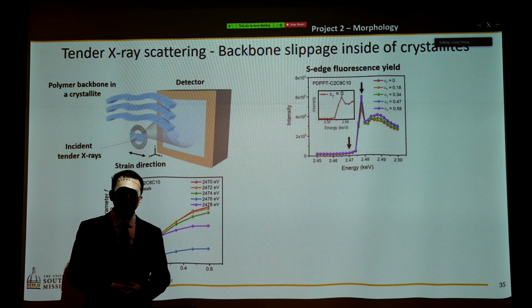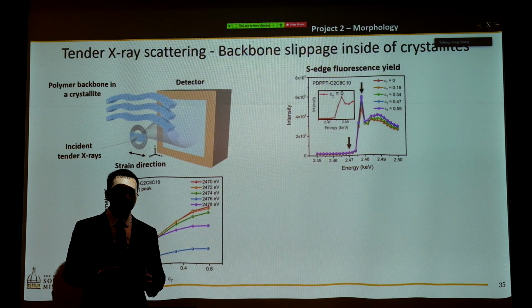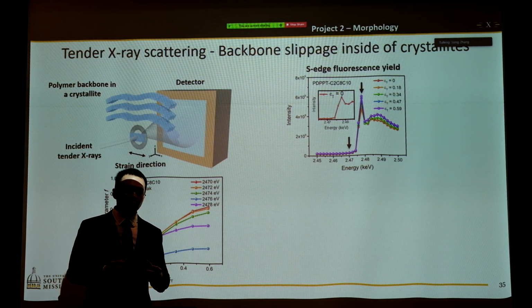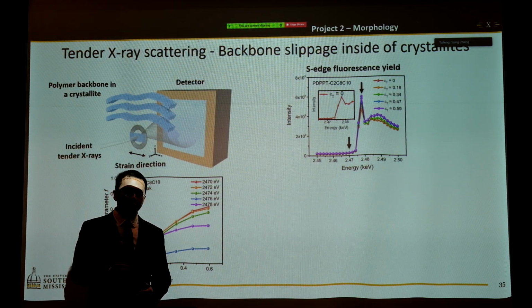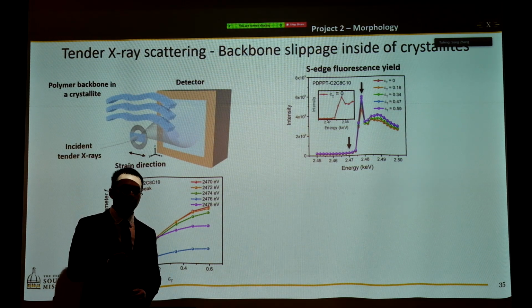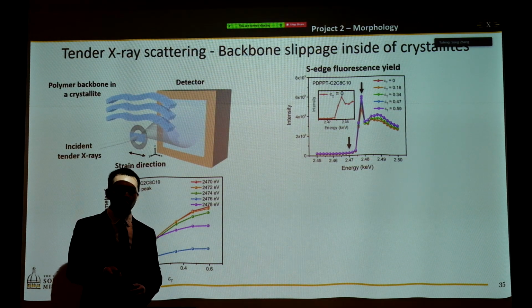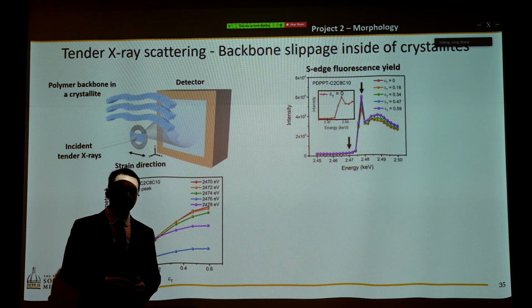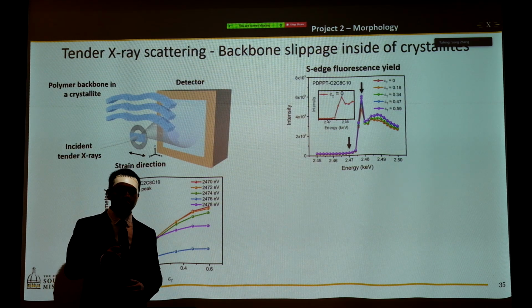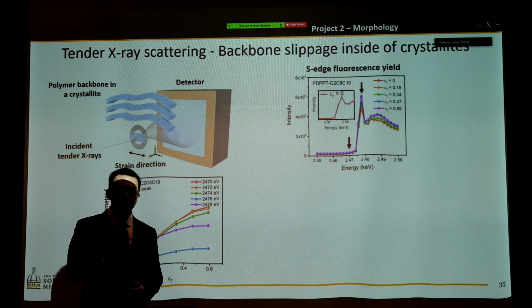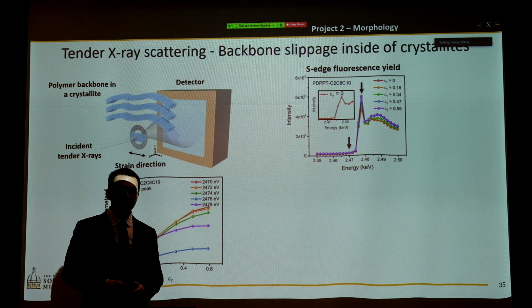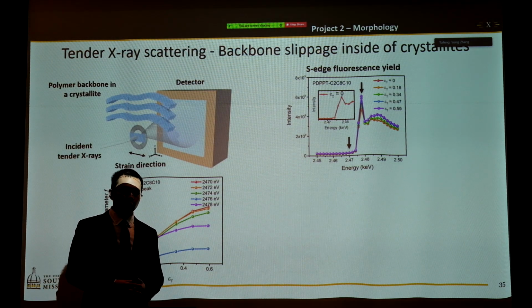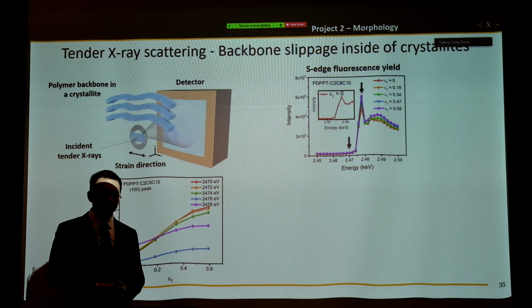Okay, now comes the interesting part. The tender X-ray scattering is giving us the backbone scattering signal in the crystallite. And as I talked about, we need to choose an energy that the sulfur atom absorbs. In the figure on the right, from the sulfur edge fluorescence yield, we can identify 2 energies: 2.47 keV, representing the onset of the absorption, and 2.478 keV, representing the maximum absorption from sulfur. So let's take a look at the orientation parameter under these 2 different energies.